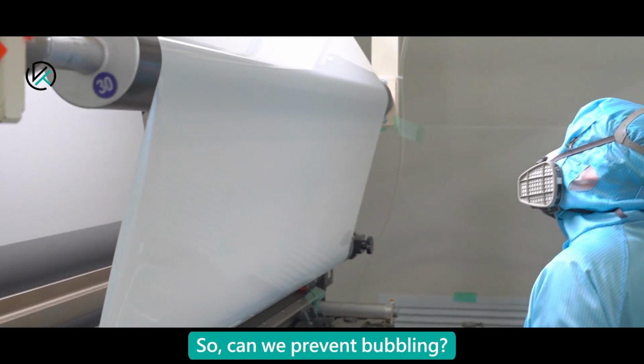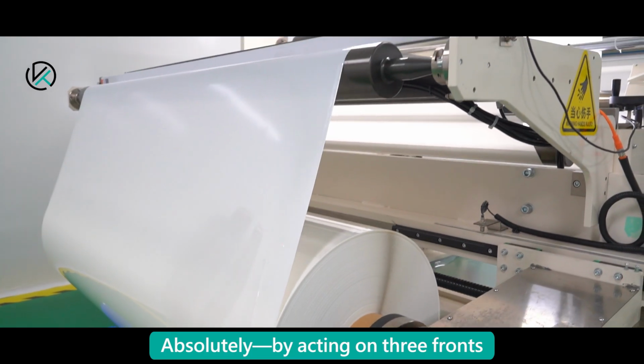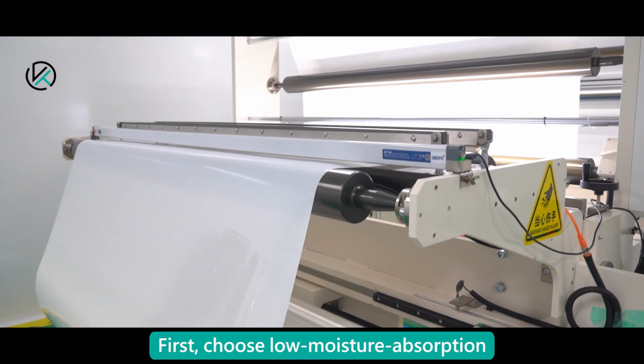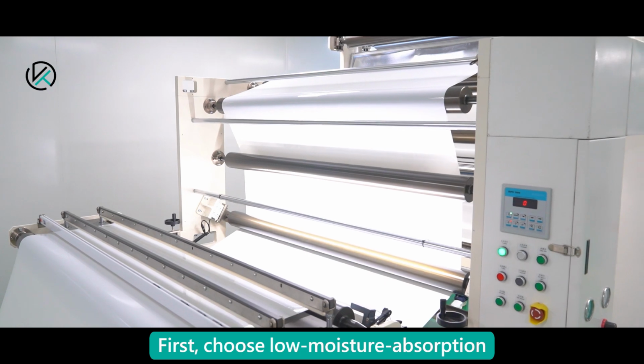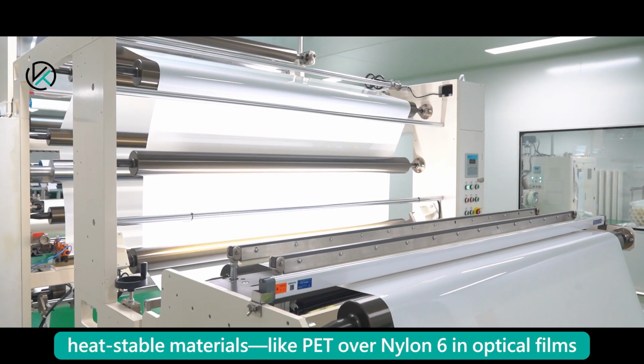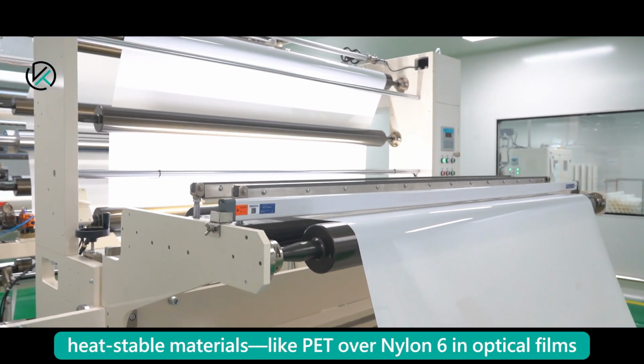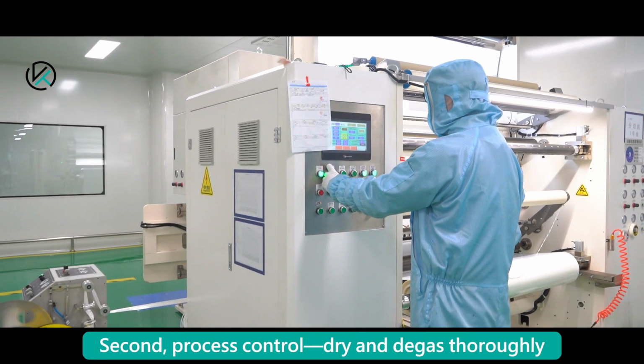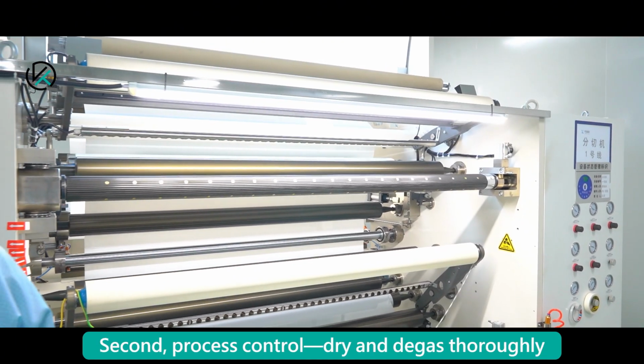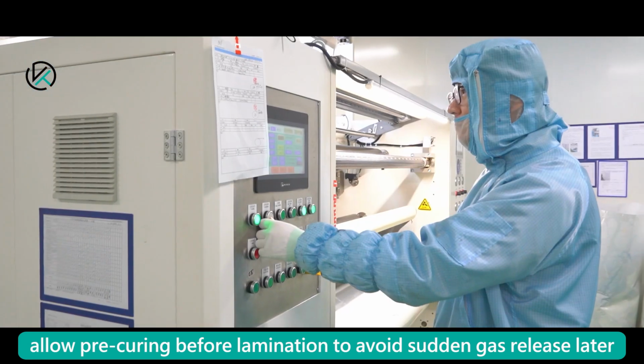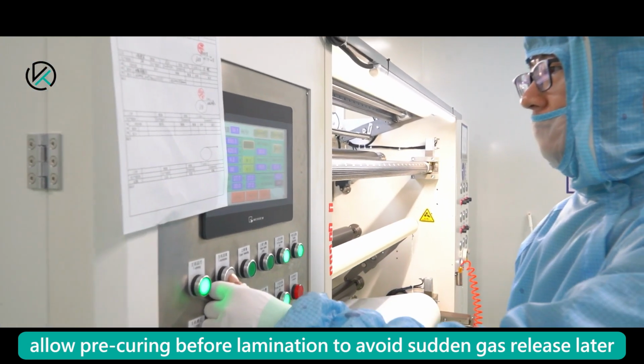So, can we prevent bubbling? Absolutely, by acting on 3 fronts. First, choose low moisture absorption, heat-stable materials, like PET over nylon 6 in optical films. Second, process control. Dry and degas thoroughly. Allow pre-curing before lamination to avoid sudden gas release later.